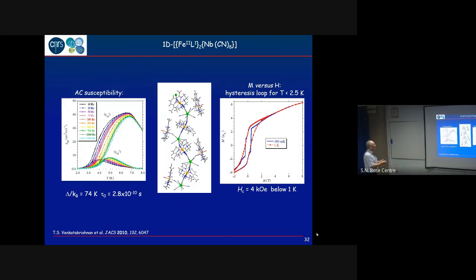Okay? And when we analyze this data, we get an energy barrier of 74. So we're quite happy to have this behavior, but I was disappointed because I expected values that would be much larger. And actually, the reason why this value is not larger is depicted here. Here, the red arrows I show are the direction of the local magnetic anisotropy. And what you can see clearly from this picture is that the local anisotropies are strongly tilted. So this is not a good situation to have a large macroscopic anisotropy.